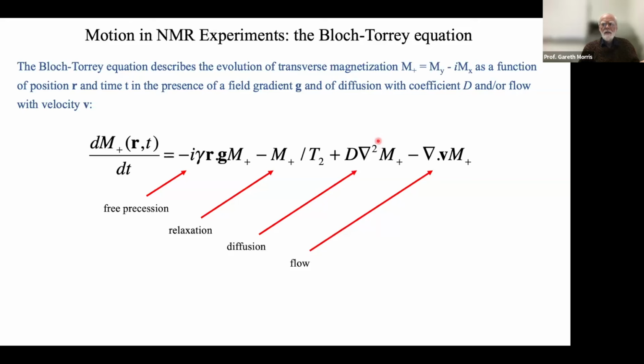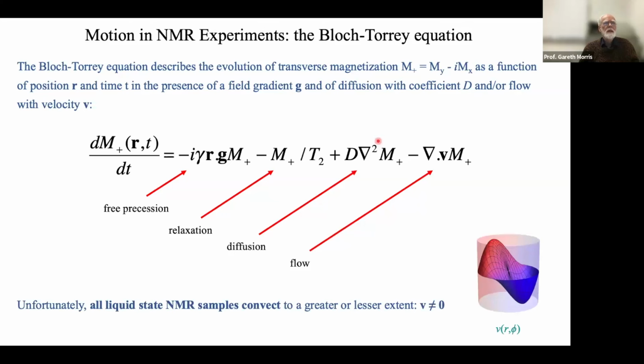Now, we might naively think that that shouldn't be a problem. We regulate the temperature in our sample. The sample's at a uniform temperature, it shouldn't convect. Alas, all NMR samples in liquid state NMR do convect to some extent. Some of them don't do it enough to bother others. Most of them do it enough to be a problem.